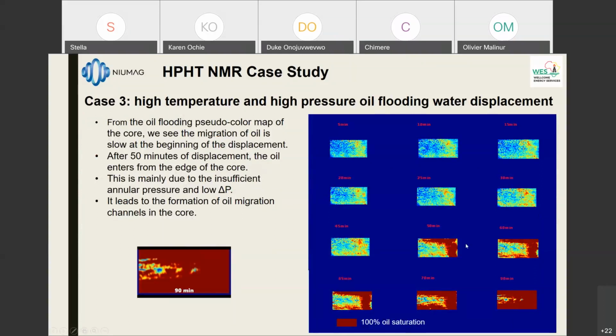So nothing is happening basically before 50 minutes, and then flow is happening, and it's going through the side of the core, passing there, and later on invading the other side of the core and leaving the center of the core like this. So the explanation I got was that it was due to insufficient annular pressure and low delta P between the annular and the core, and the pore pressure.